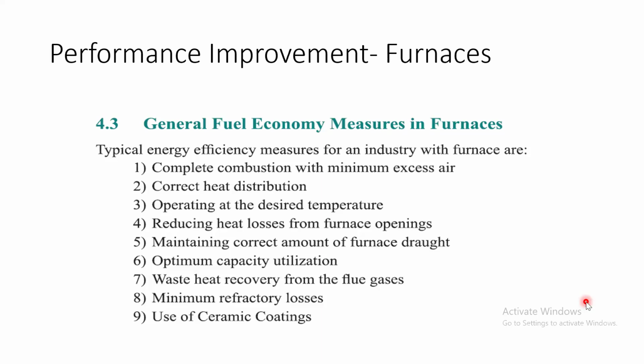Then minimum loss of refractory is also very important. Waste heat recovery is as usual very important. Then complete combustion with minimum excess air, for which I have already explained the percentage. Then correct heat distribution. Uneven heat distribution will lead to the rejection of partial batches, and all such parameters are very important for the fuel economy in furnaces. Okay, so all other losses like loss from openings, loss from the walls, loss from the refractory insulation and all that, if you are able to control or save these, your furnace efficiency will improve a lot. Okay. Okay, sir.